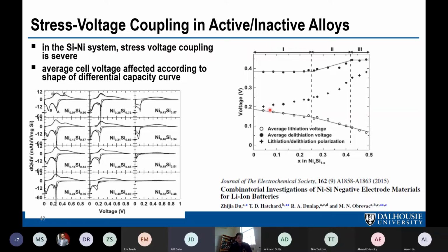You just get this stress potential coupling, which is seen during lithiation. But then you start chewing away at that first peak, and it's affecting the delithiation now. And then you get into the region where this peak is completely gone. And then you're in the valley between the two peaks, and again, nothing much happens. So this is the shape of the average potential versus nickel content, and it is because of the shape of the differential capacity curve.